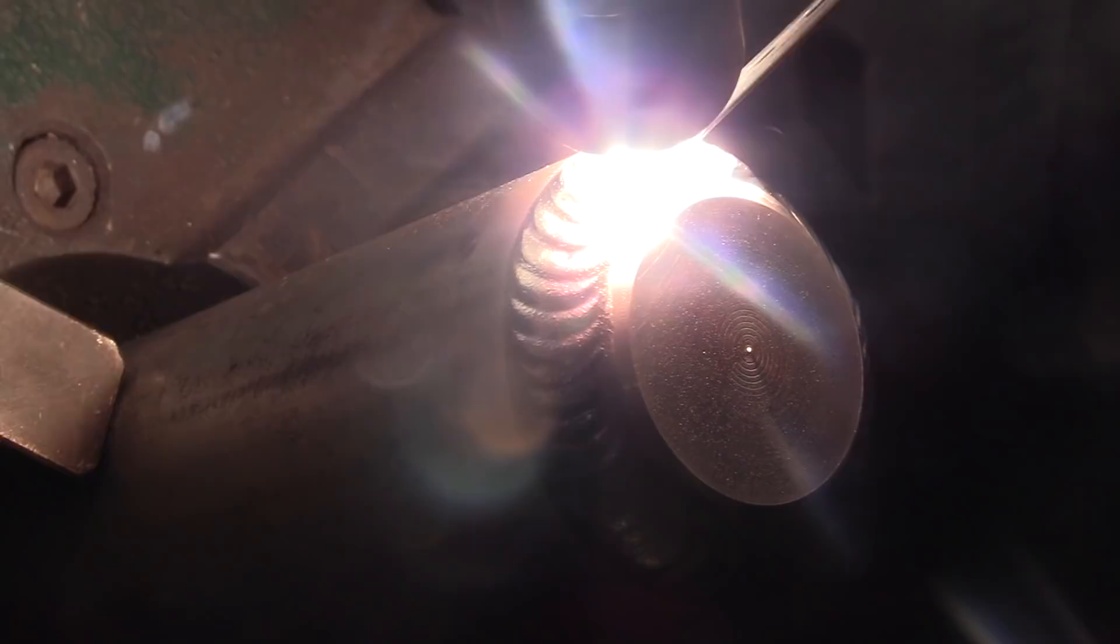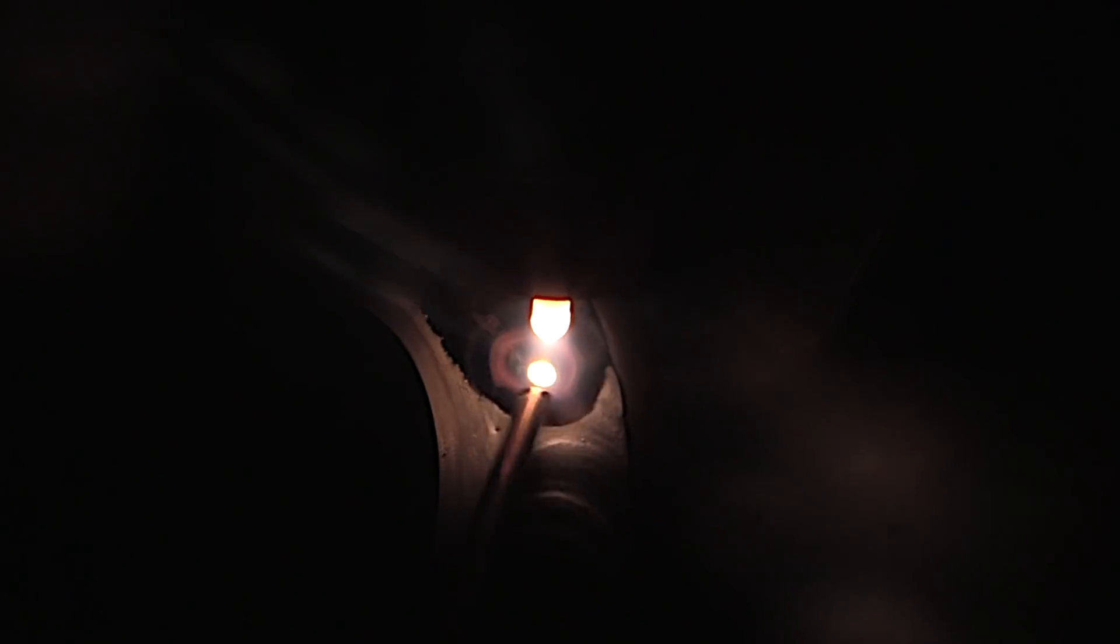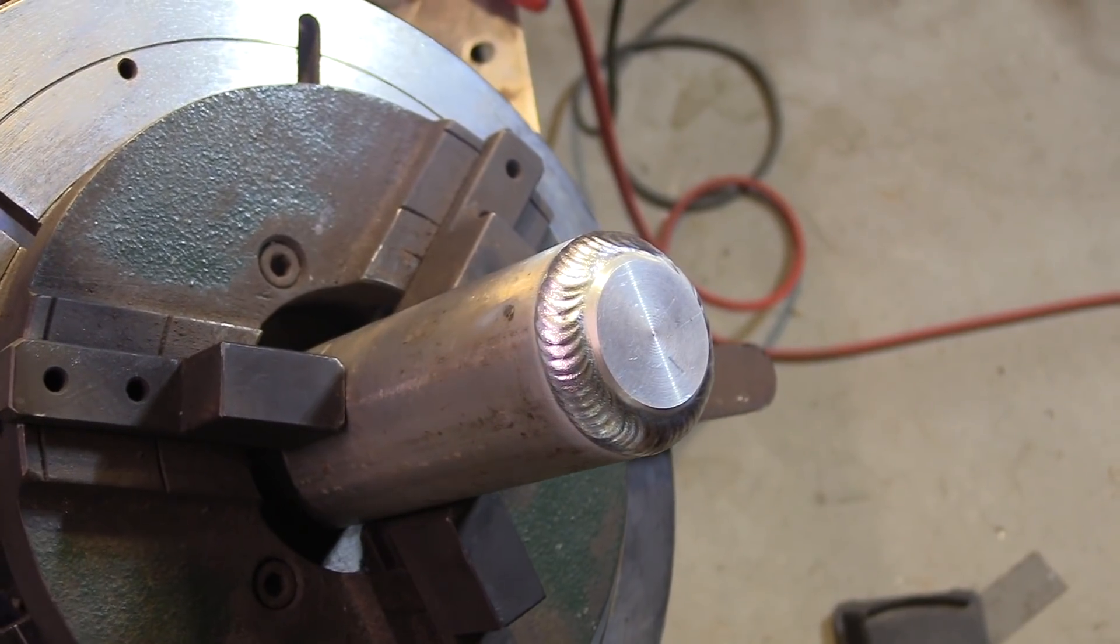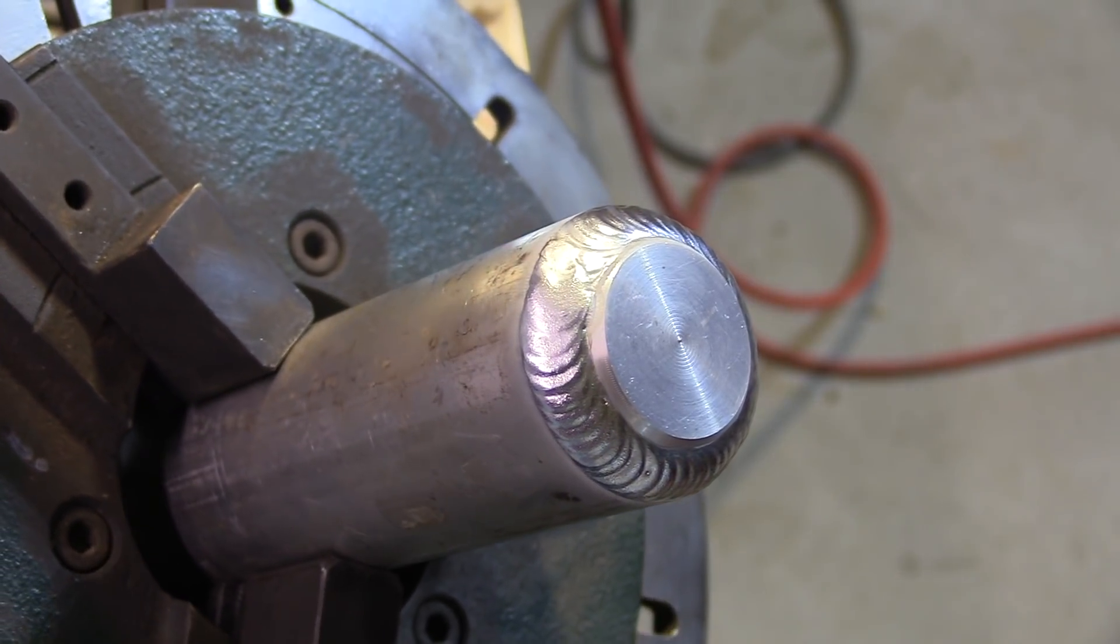You can see I'm hovering around 175 to 185 amps for most of this. The puddle is pretty clean. That's a solid plug I'm welding in there. Once I overlap two or three ripples, I taper off and wiggle the arc around to not leave a crater crack.